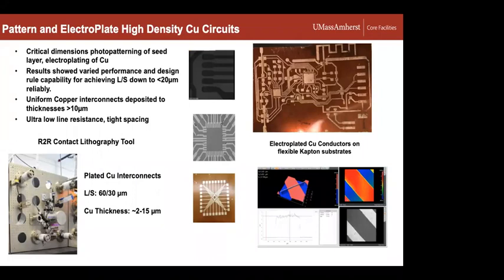for example. And in the lower right here, we just show an imaging profilometer measurement of an example thickness of a line, again, on the order of about 11 microns in this case, and a pretty good crisp line with a pretty smooth surface. And that's another thing, a lot of times these silver inks have very rough surfaces, which could impact attachment of silicon die or other integration.